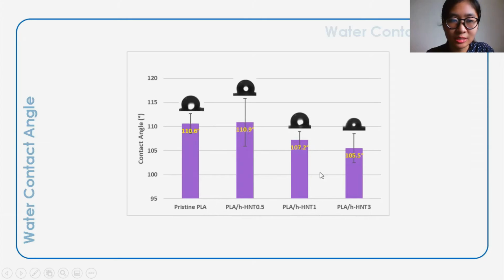However, since the measured contact angles for the electrospun fiber mats are greater than 90 degrees, the wettability of the mats indicates a hydrophobic surface. Although halloysite was functionalized by alkali treatment to increase the density of hydroxyl groups on the external surface of HNTs, it has little contribution to the overall hydrophilicity of the polymer matrix. Increasing HHNT content in the polymer matrix may increase hydrophilicity, however, it causes the tensile strength of the composite mats